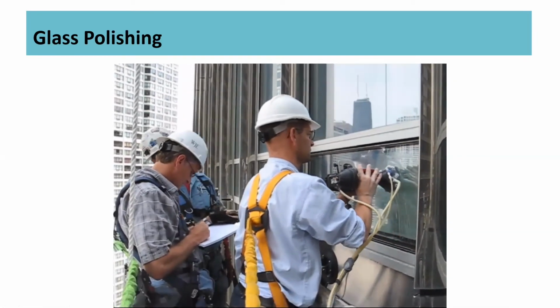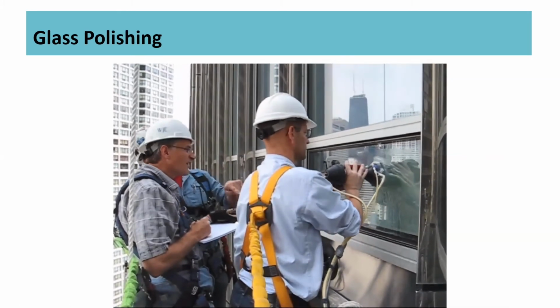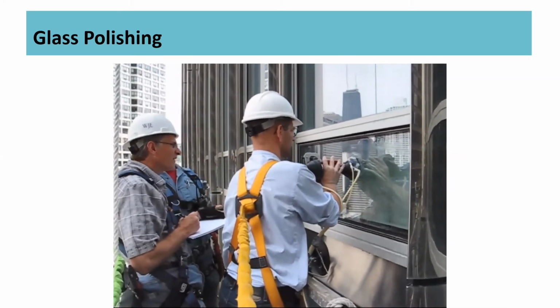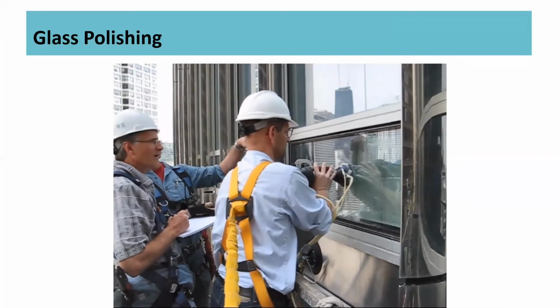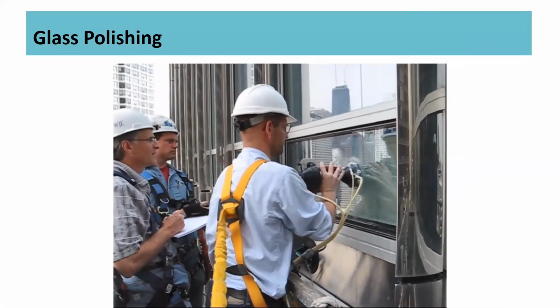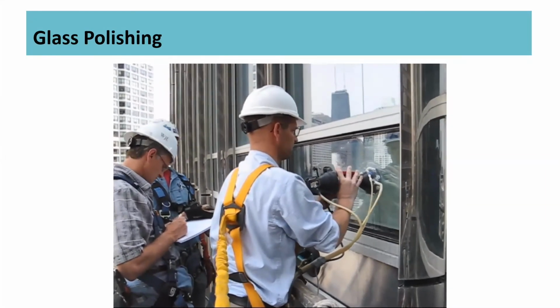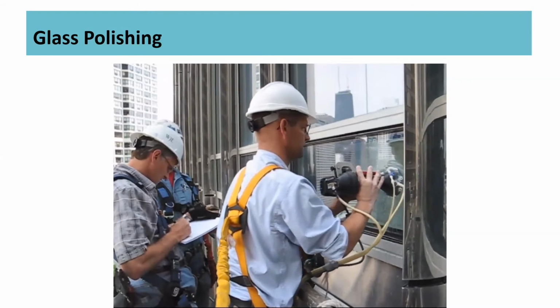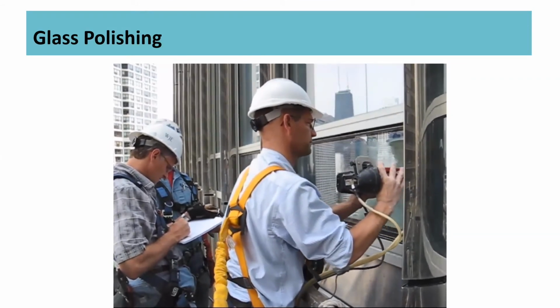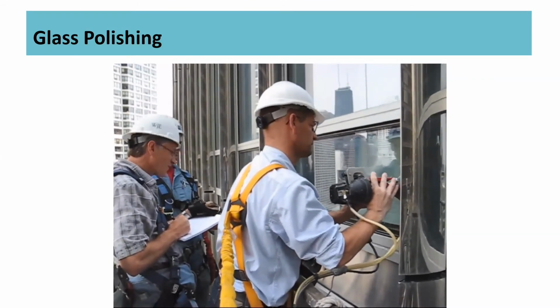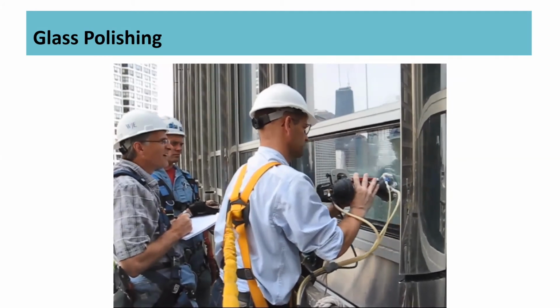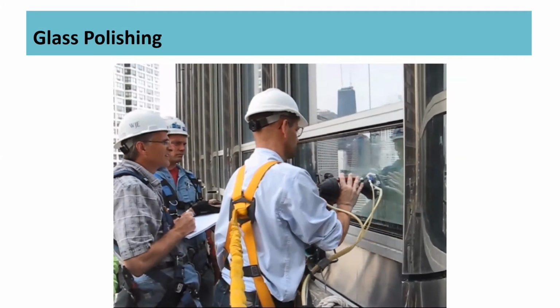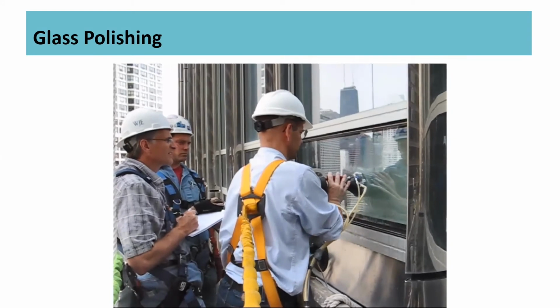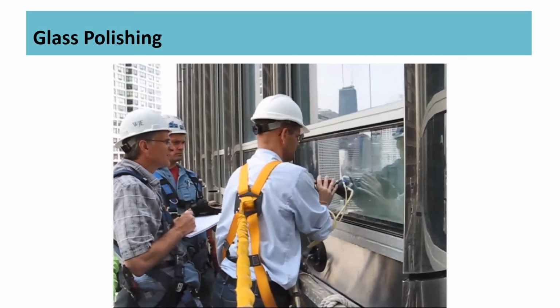It's an automated polishing procedure where there's a shrouded area that you can see of the device. Underneath the shroud is a spinning felt pad, and cerium oxide slurry is being recirculated under the shroud, under the pad, and back to a bucket. So this process we found is less workmanship critical.